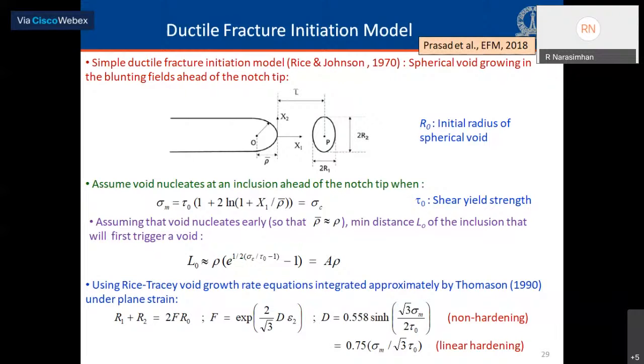And at a particular stage of deformation, it has become ellipsoidal in shape with the principal radii R1 and R2. We assume that this void has nucleated from an inclusion when the mean stress sigma m, which is given by this logarithmic expression here from the logarithmic slip-line field, reaches a critical value sigma c. This gives rise to a relationship between the nearest void nucleating particle L0 and the notch root radius by the equation in the middle of the slide. And following the Rice-Tracey void growth rate equations, which were approximately integrated by Thomason, we can write the sum of the principal radii as related to the initial void size R0 through this expression 2f times R0, where f, the parameter, exponentially depends on the normal strain as well as the mean stress.